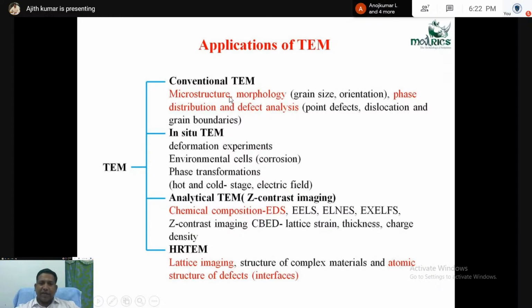Conventional TEM means for nano-sized microstructure and morphology. Small grain size, nano grain size, or orientation we can see using conventional TEM at nano scale. And in situ TEM means during the TEM experiment, we can see the deformation. We can see the environment effects, like corrosion, in situ we can see the video. And phase transformation: during heating, if you do in situ TEM, then we can get the phase transformation video.